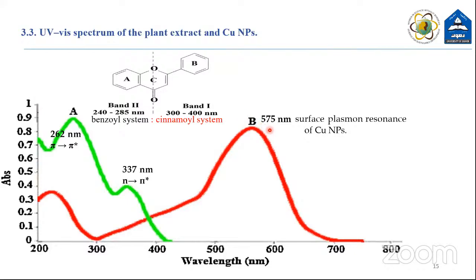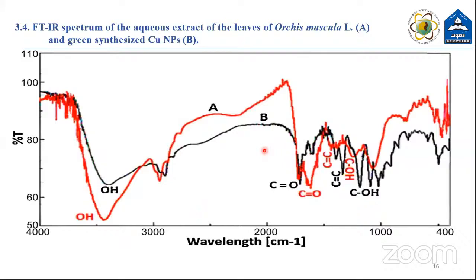The peak at 575 nanometers indicates the surface plasmon resonance of copper nanoparticles. And this spectrum starts near UV, as you see. This indicates that these nanoparticles are synthesized through a green method, and this is absent if the method is non-green. For example, for physical or chemical methods, we cannot see this; only the signal will be in the visible. The presence of the functional groups of phytochemicals in spectrum B, the spectrum of copper nanoparticles, indicates that these phytochemicals are adsorbed on the surface of the copper nanoparticles. A is the spectrum of plant extract, and B is the spectrum of copper nanoparticles.